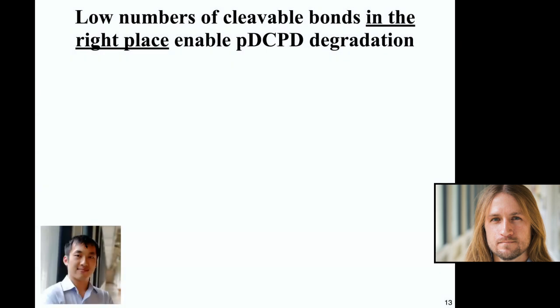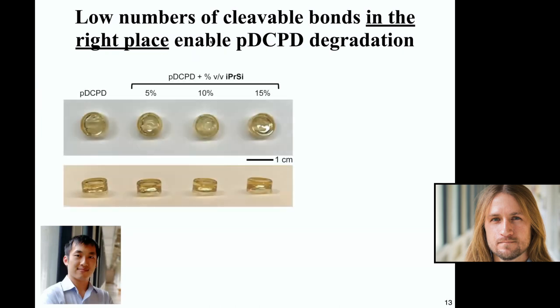And Peyton Shea, a postdoc in my laboratory, went in and did this experiment and found really striking results. Namely, that low numbers of cleavable bonds in the right place enable PDCPD degradation. So here are a series of samples that Peyton made where he compared just pure PDCPD with none of our additive to materials made with 5%, 10%, and 15% by volume of our silicon-containing molecule we call IPRSI.